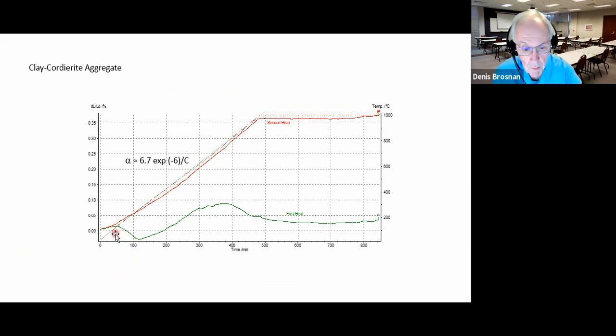Anyway, if you took the powder itself, a formed object from the powder, and checked the thermal expansion, it's going to shrink a little bit at fairly low temperature when some of the binder decomposes. Get up to dehydroxylation, it's going to lose shape again, lose some expansion again. So this is not a good way to evaluate that. If you heat it up and soak at elevated temperature, as I did here, and then heat and cool it, we have reversible thermal expansion. And we got about 6.7 times 10 to the minus 6 for the thermal expansion coefficient.